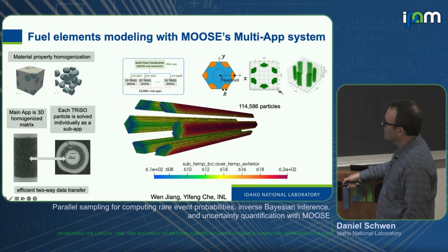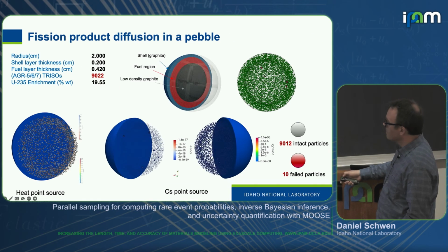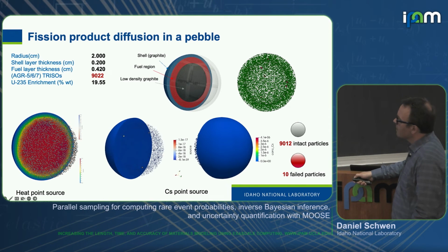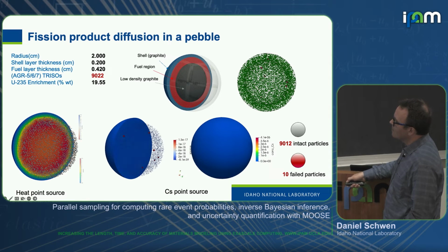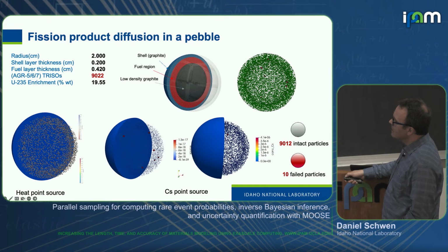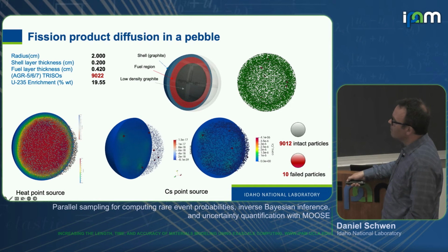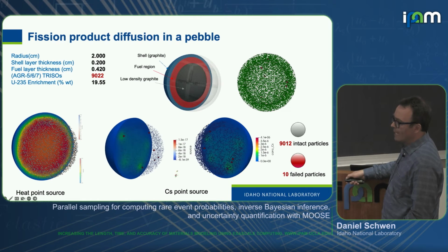And my colleague Yifeng Che, she did this for a microreactor geometry here. There's a lot more to the simulation than I can say in a minute, but again, this is over 100,000 particles, two-way coupling. You can get the thermal distribution, species distribution. So this is a TRISO pebble with, again, lots of TRISO particles in it. With the failure probability that we've calculated earlier, we know that there are a couple of TRISO particles that would have failed in this particle.